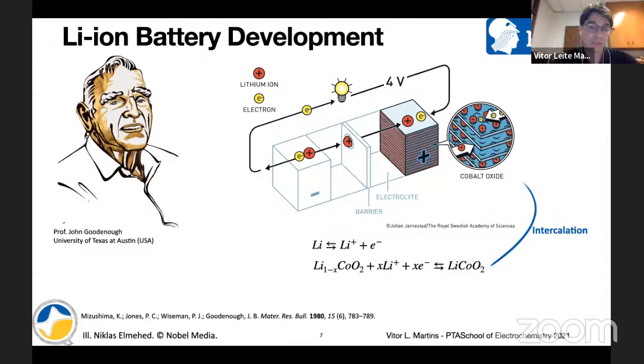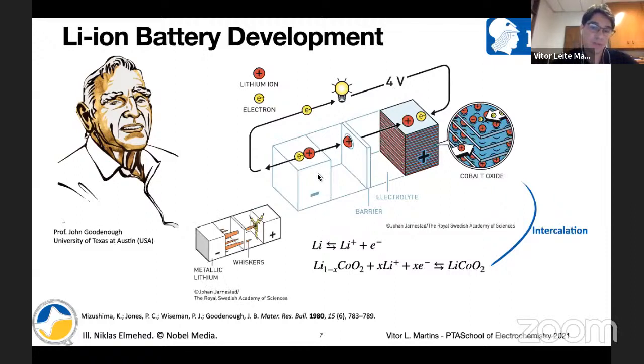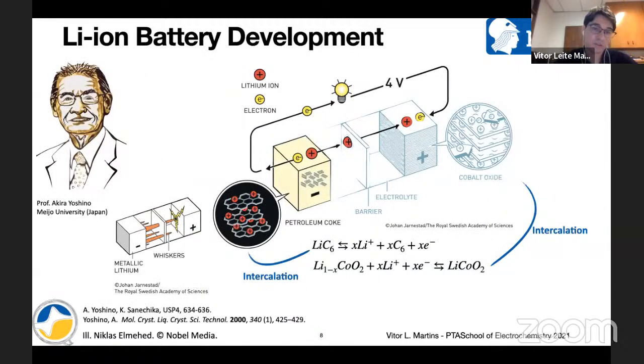The problem of this system is that using metallic lithium, you grow some dendrites during oxidation and reduction of lithium. Those dendrites grow through the cell and can go through the separator and touch the other side of the cell. This will cause a short circuit and can cause fire. So this was a bottleneck of this technology. And Professor Yoshino made his contribution on this part.